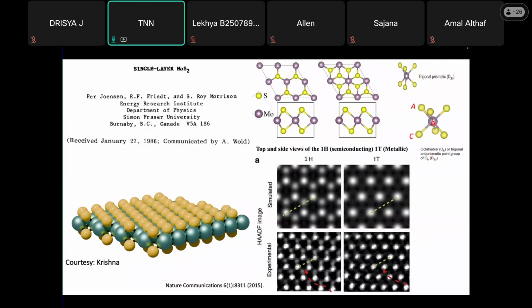Sulfur has a lower atomic number than Mo, and in the transmission electron microscope, particularly if you look into the diffracted image, you know that contrast depends completely upon the atomic number of the material. So sulfur has a very low atomic number. You will not see the sulfur column if both sulfurs are not in the same line. You think that you are looking from the top and seeing the transmission of a monolayer system, so whatever you are seeing will be exactly like what is arranged in a plane, right? Now, since in the 1H case both the sulfurs are on top of each other, you will see a sulfur column there, and both the sulfur and molybdenum columns will be visible.